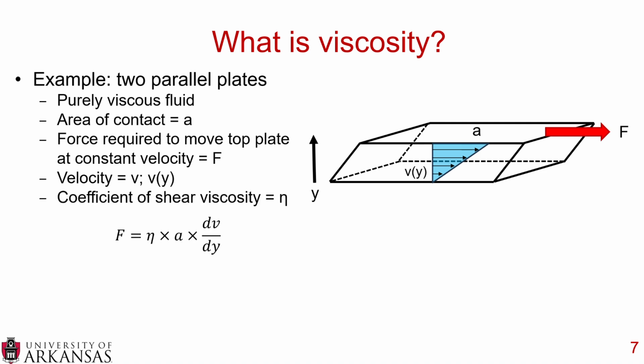There is a coefficient of shear viscosity, eta, and the force equals eta times A times the change in velocity over the change in height. So that's a fundamental principle correlating the deformation to the force. And the strain rate is epsilon dot, which is d epsilon over dt, which is equal to dv over dy.